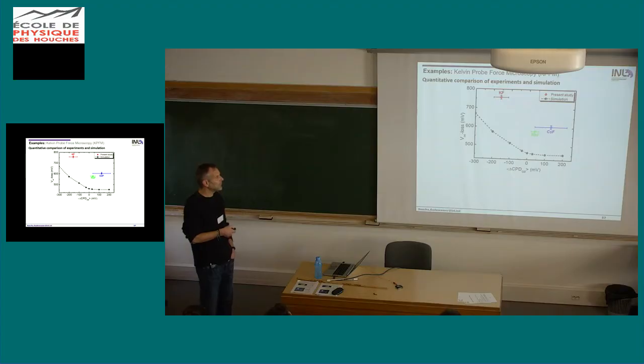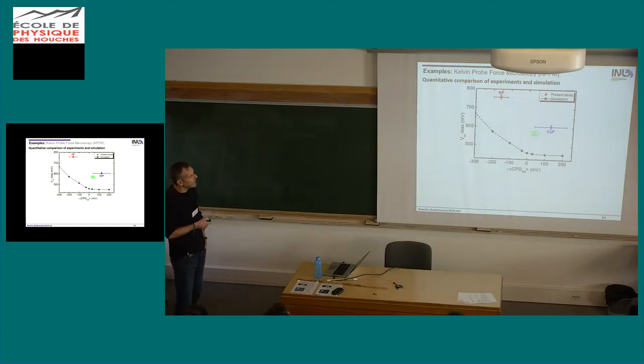And then we also know for our very samples where they are, how much open circuit loss we have with respect to the band gap. And we know from our images the average CPD change at the grain boundaries. We get these plots which follow more or less the trend of this line, but everything is above this line. So there are more processes that lead to loss in the open circuit voltage. It's not only the grain boundaries, obviously, whereas here we only consider what happens due to the grain boundaries.